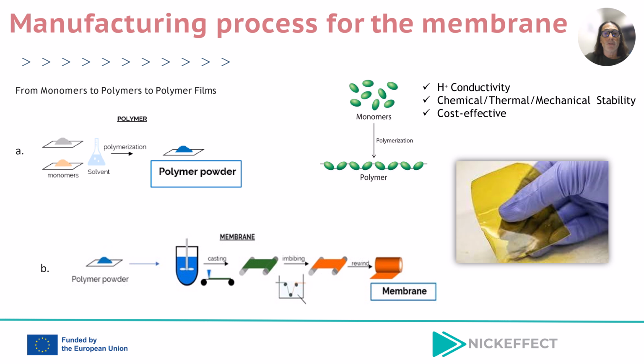It needs to remain stable under the fuel cell's operating conditions, temperature, humidity, and chemical exposure over long periods. A thinner membrane improves proton transport but may be fragile. A thicker one is stronger but can reduce conductivity. So we aim for the right balance. We want to minimize the leakage of hydrogen or oxygen through the membrane. High crossover reduces efficiency and can pose safety risks.